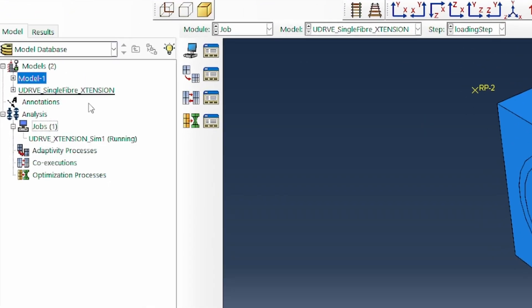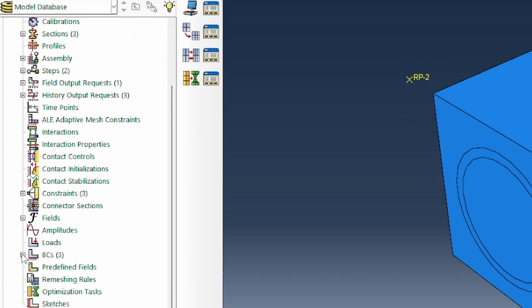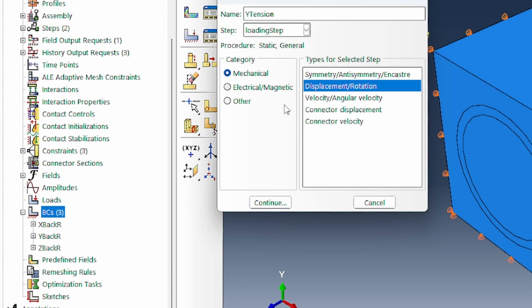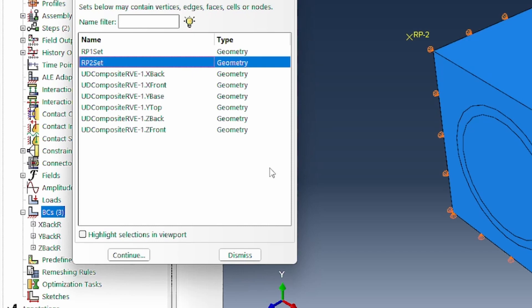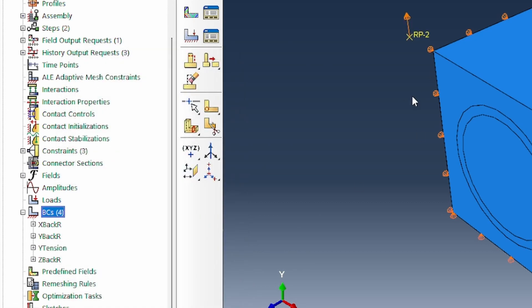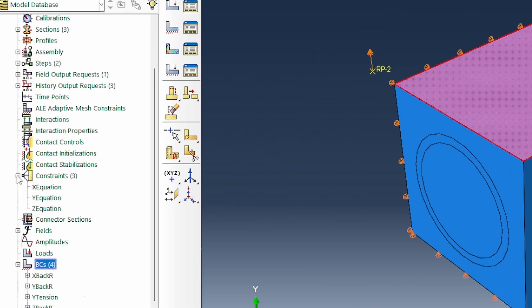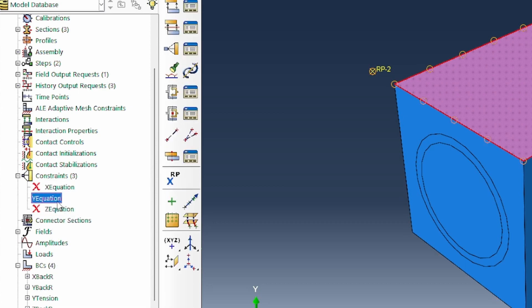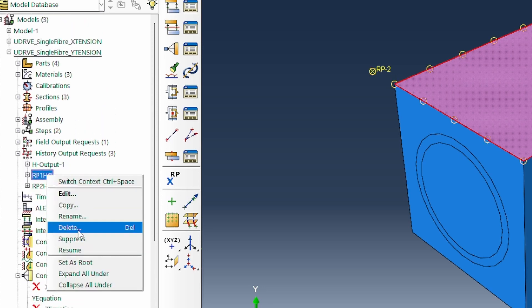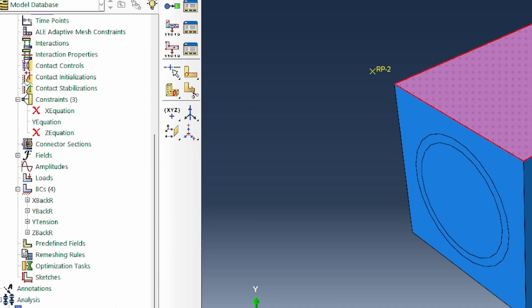For y-tension, I use the original model and create a copy. The boundary conditions remain the same. A y-tension load is applied, associated with a loading step linked to reference point 2 in the y-direction, again with a 10 micron unit loading. This load is translated to the y-top face via the y-constraint equation. The x and z constraint equations are suppressed, and history output for reference point 1 is suppressed, leaving only reference point 2. The job is submitted.